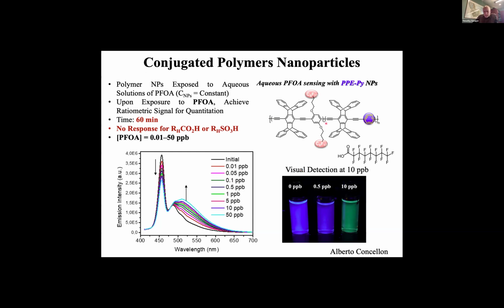So we have a polymer here. It's got perfluoroalkyls. This one has these little wings to give it some porosity, which we find to be kind of useful. And what you see is as we add PFAS to this, we get a decrease in one emission band and an increase in the other. So the decrease is in the emission of the polymer that is unperturbed by the PFAS, and the increase is of sites that have been activated by the PFAS that are giving us this green color. And so you can see it highly activated at 10 parts per billion, and it's all green. And then you need an instrument in this case to detect these other smaller changes.